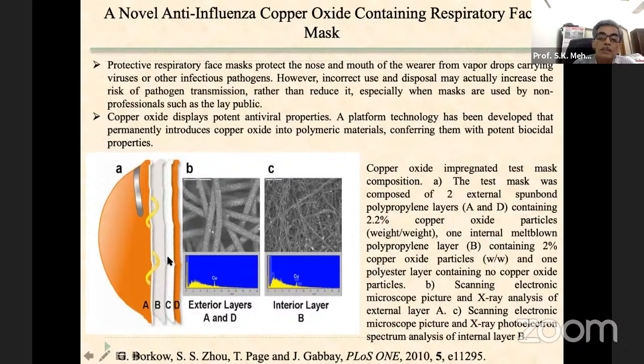I will also tell you about our experience in this. This way you can easily protect yourself, because when the virus comes in contact with the copper oxide particles, it will die automatically. It will interact with the particles, its receptor will become inactive, and there is no chance it can go inside your mouth or nose. They have shown the external layer is a thick thread type, and the inner one is also thread but thin, and you can see the presence of copper. One can easily see from the SEM photographs clear copper oxide particles on the layers. So this is very useful.